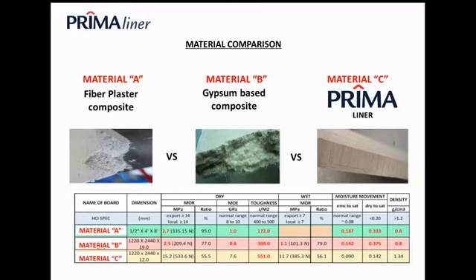Let's look at the dry to saturation situation. 0.03, 0.33, 0.375 versus 0.142. Again, similar character when it comes to dry to saturation. Why? Maybe it's because of the density. Material A is 0.8 gram per centimeter cube. Material B is also the same, but material C is 1.34 gram per centimeter cube, or 1340 kg per meter cube. Okay, so that explains why the cross section looks like that.